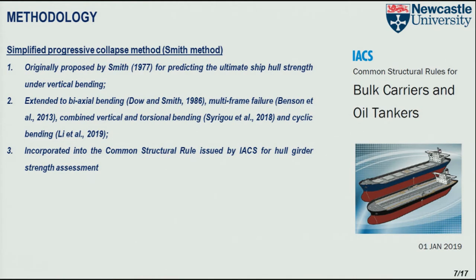And this Smith method, the simplified progressive collapse method, is essentially a further generalization of the elementary beam theory. In this methodology, there are three assumptions. First is the beam assumption. The cross-section remains plane during the progressive collapse. That means we are dealing with a pure bending problem. We do not consider effects like warping and shear lag.